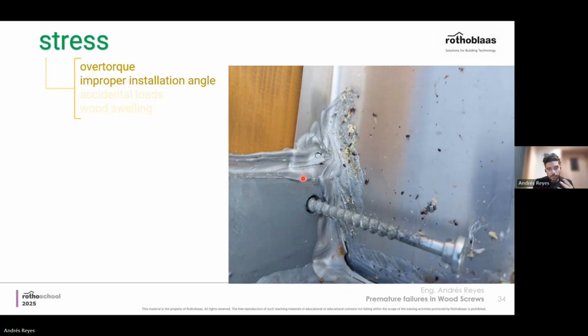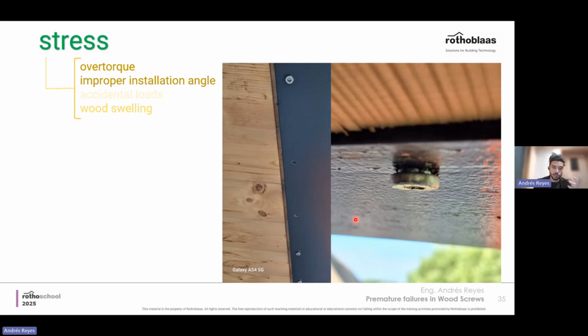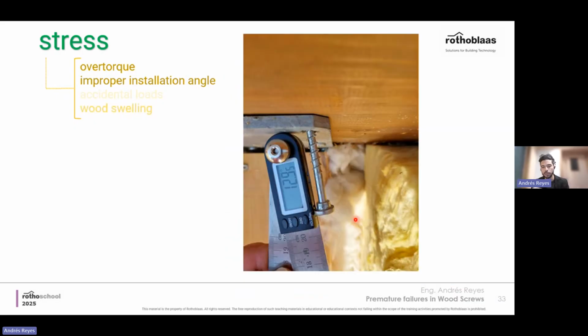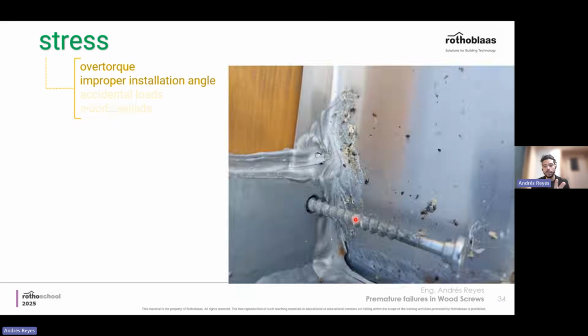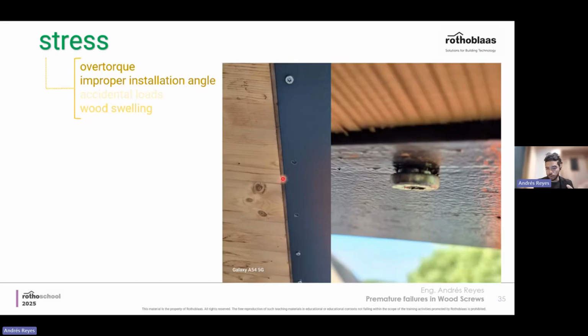In many cases, coming to corrosion due to over torque and improper installation angle, you could even see the corrosion signs. In this case, it's not yet the red corrosion, the rust that you see in some cases, but white corrosion is present, and you see the phenomenon starting to happen. Finally, wood swelling as well as a stress factor. We also need moisture in these cases. There's also wood swelling here, with an improper installation angle. Wood swelling, the signs of moisture here happen.